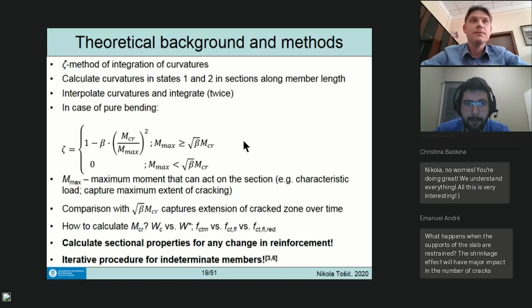Calculate curvatures in states 1 and 2 along the member length, interpolate and integrate them twice: once to get inclinations, and a second time to get deflections. In case of pure bending, and since I'm focusing on buildings it's going to be pure bending, you can reformulate your Zeta distribution coefficient not in terms of stresses, but moments.